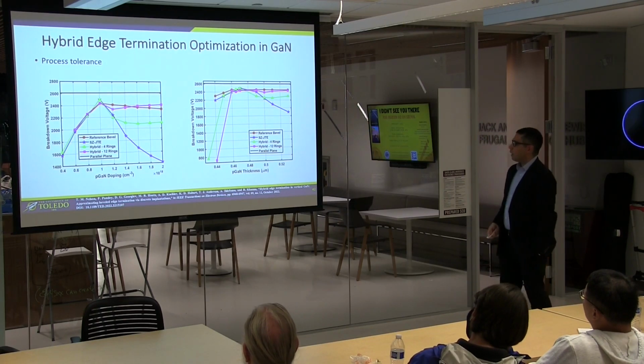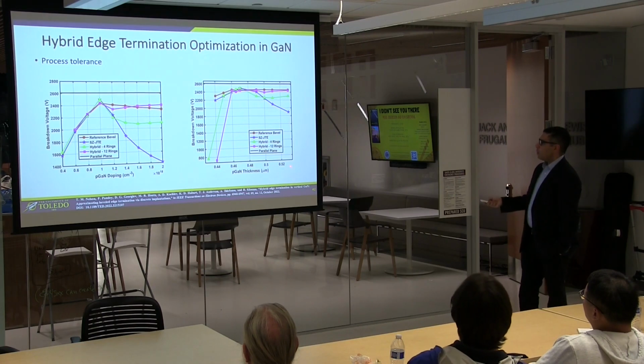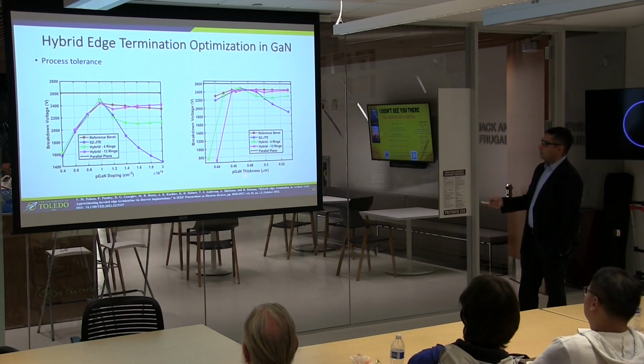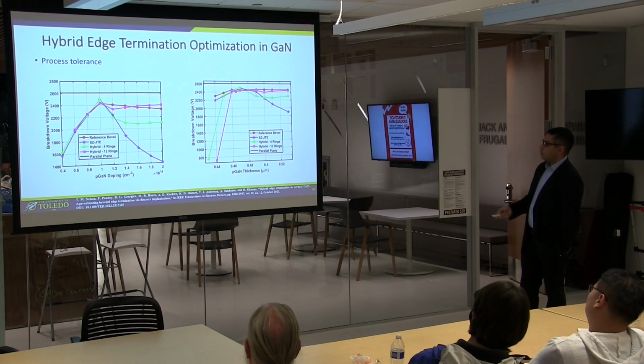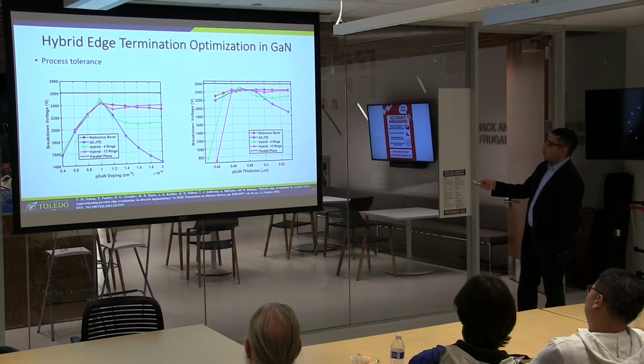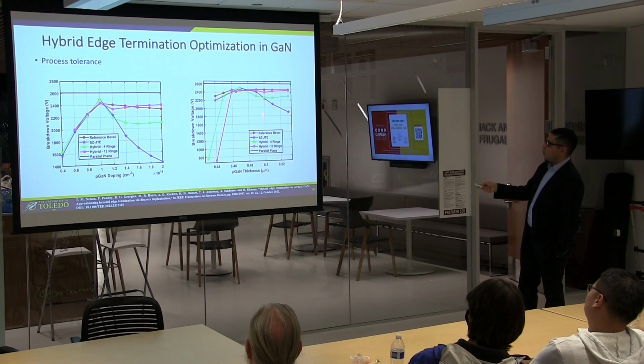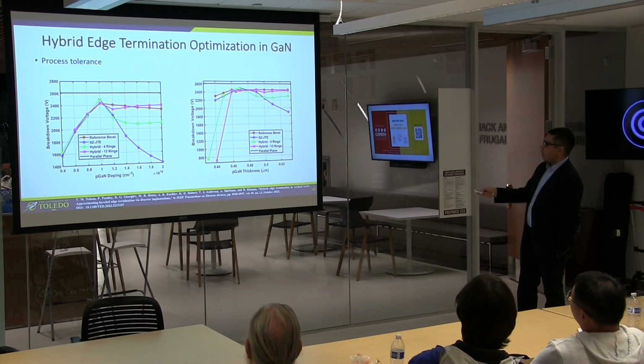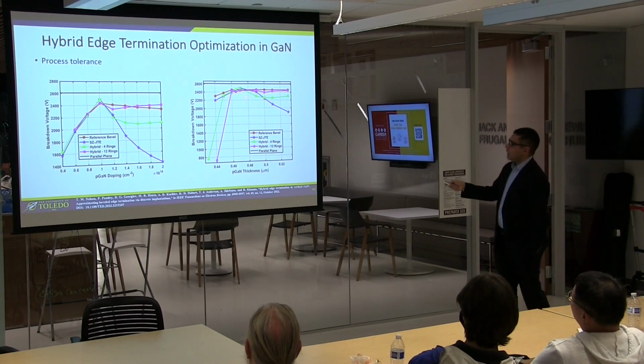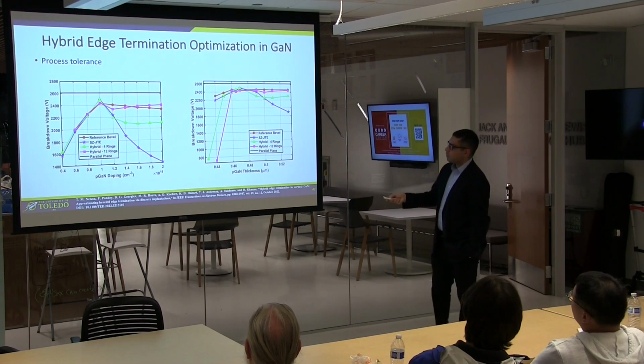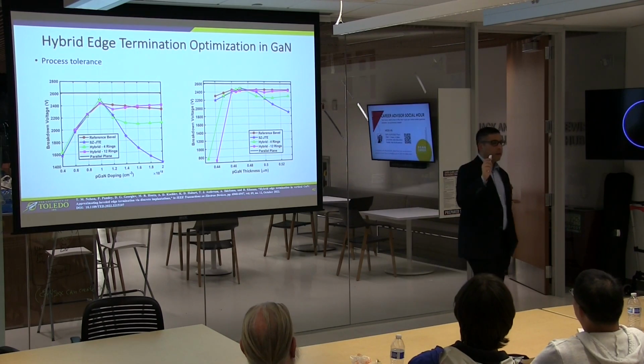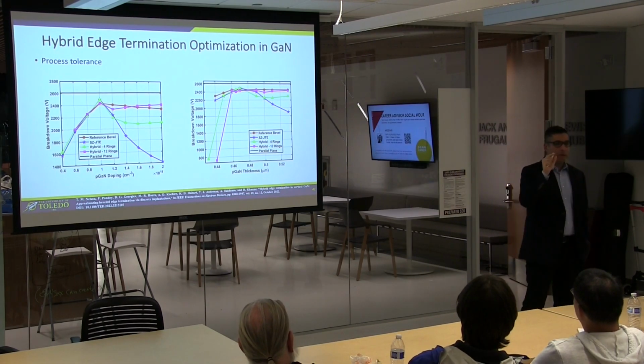What about the P-GaN thickness? Breakdown voltage versus P-GaN thickness. Again, the important one here is the reference bevel, and then you're looking with the magenta as well as the green. So the green is now the 4-ring structure. Oh, here's the trade-off. The 12-ring was a little bit less breakdown, you might recall.